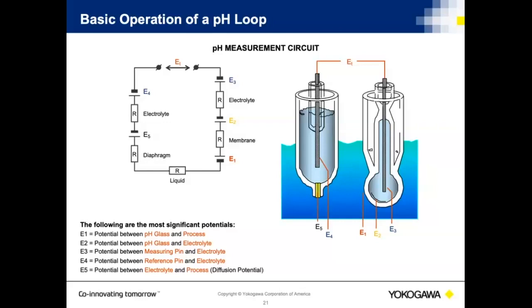I won't go into the detail here because it gets into some pretty nasty circuit analysis. The reality is what you have is a voltage that is developed between the 2 electrodes. One is the reference electrode on the left, and the other one is the measuring electrode. And they're both basically silver-silver chloride electrodes. The reference electrode is immersed in a potassium chloride solution, whereas the pH silver-silver chloride electrode is immersed in a 7 buffer solution. The point is the reference probe makes contact with the solution. The measuring electrode is actually where we make the measurement.